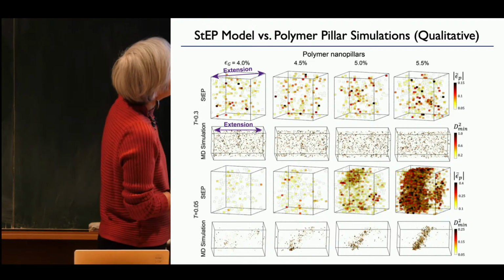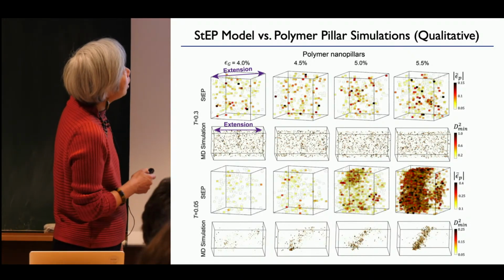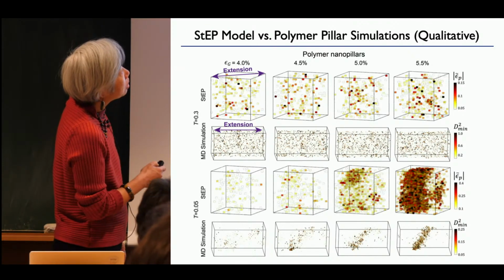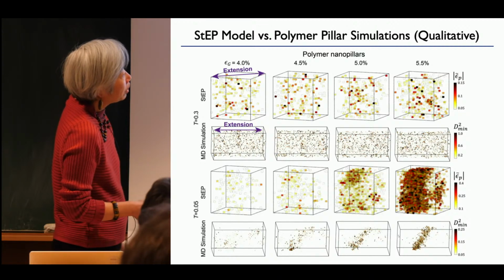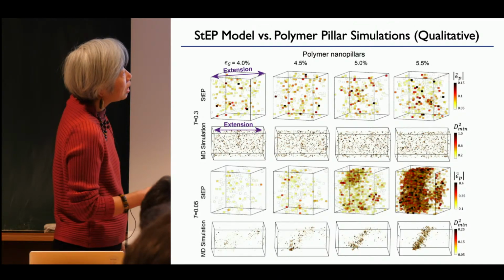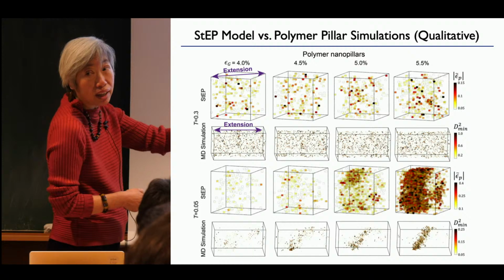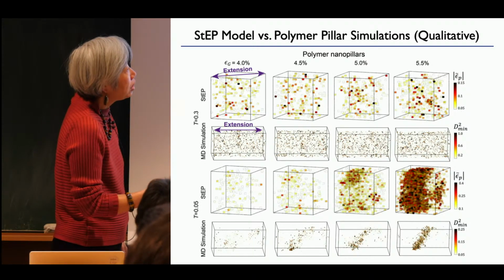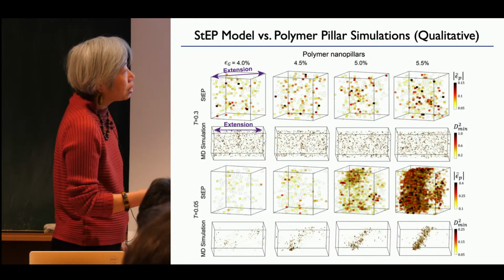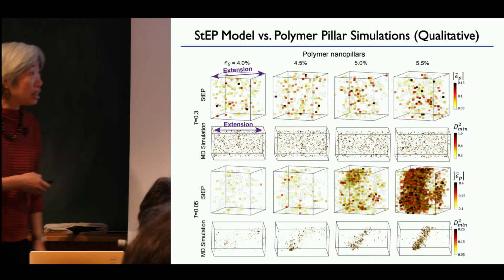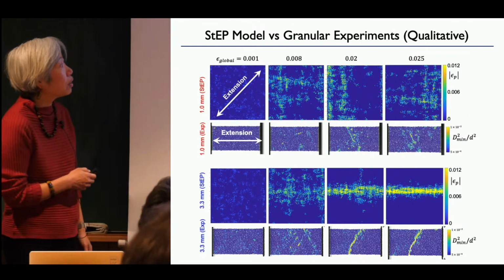Let's see. Here are the polymer pillar simulations. Here are the simulations. Here's the step model. Here are the simulations showing much more strain localization. This is as a function of strain. You see it developing and concentrating in this plane, and it's done. Am I done? I'm out of 5 minutes.